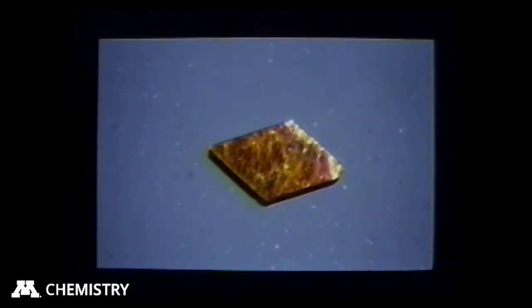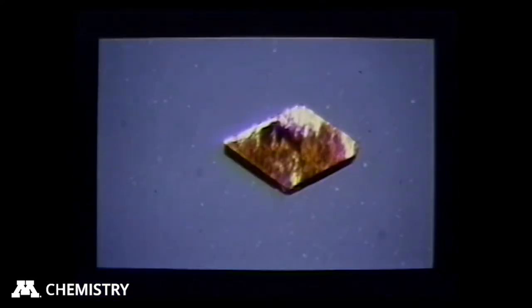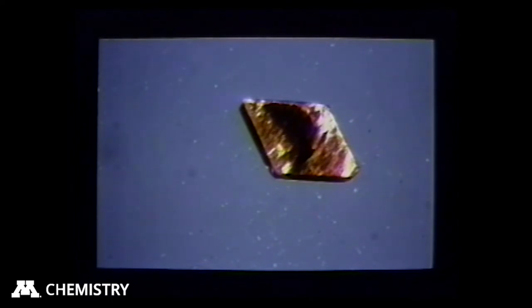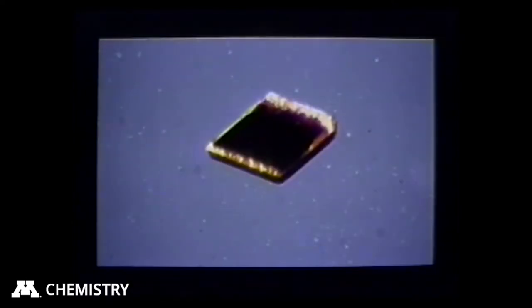So this is actually a fairly true color. It's basically an orange crystal. The reflections you see on the edge are not relevant to the phase transformation. That's just a reflection. But the sort of dark colors that you see starting to grow in here and the purple color up here are actually the product phase. So some kind of a transformation is taking place over a period of time. And here we see more of the product phase growing in. Some purple regions there. Now you see a lot of product phase in the middle, very high contrast. And finally, a crystal that is basically completely transformed.